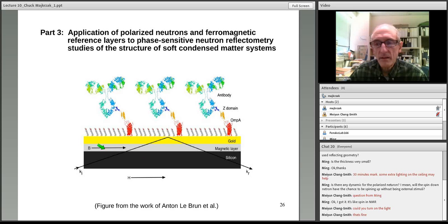Remember, we talked on Wednesday about the idea of using reference layers or reference substrates to do composite reflectivity measurements for two reference values, to be able to isolate uniquely the reflection amplitude that comes from the system of interest, so we can directly invert it or solve simultaneously in such a way that we can get a unique answer, an unambiguous scattering length density profile.